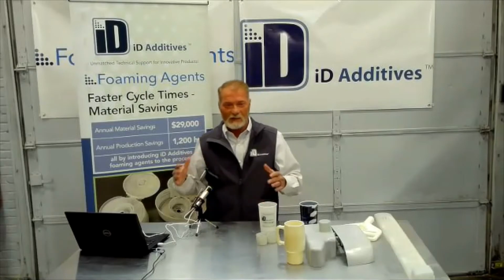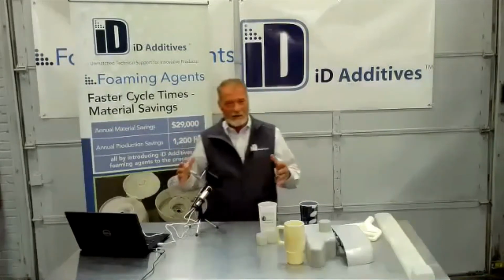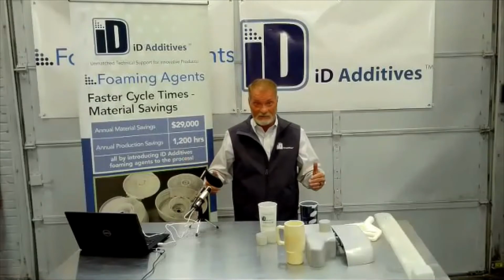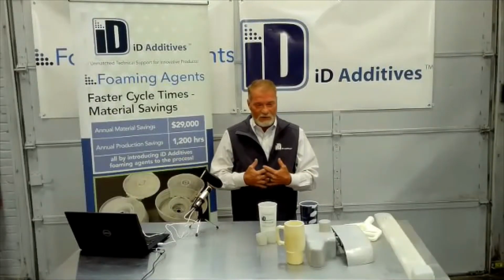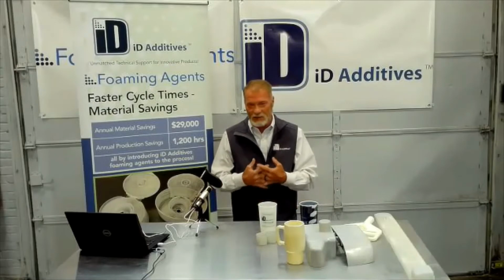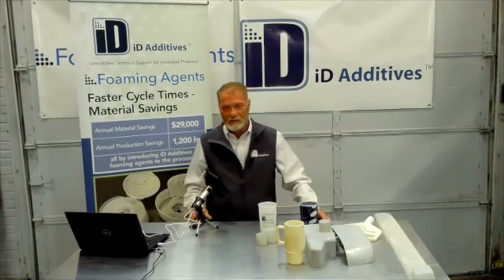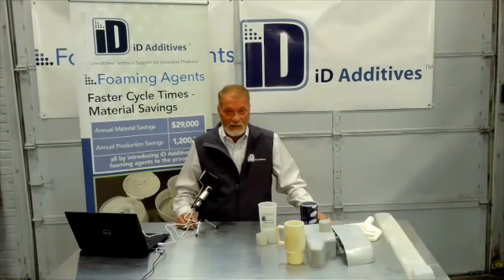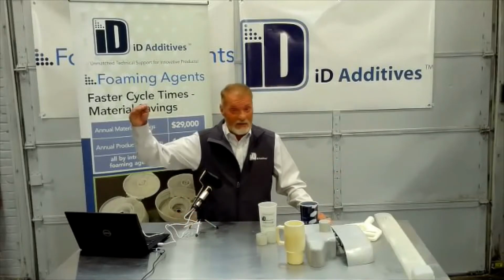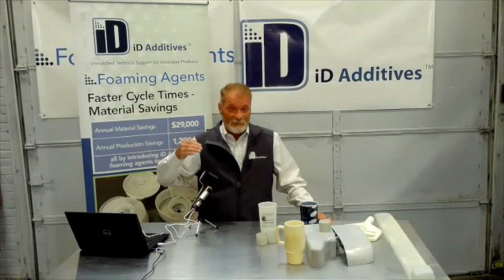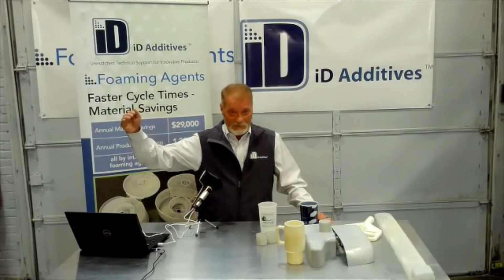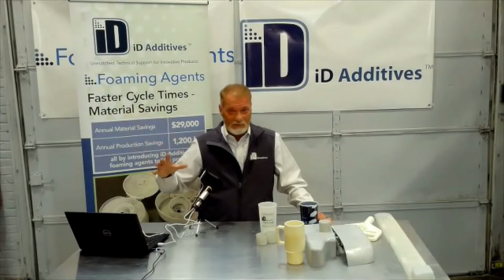If you want to do high aesthetic parts, you've got to get it in extremely fast. The faster, the better. So if you just wanted to do an aesthetic part and I come into your facility, I walk up to your machine, if you're injecting the part at, I don't know, 4 or 5 inches per second, and you could do 10, I'm going to push to that 10 inches per second. The faster, the better.